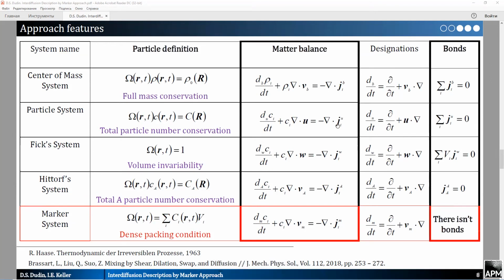The mass balance equations for components written in terms of the total time derivatives have the same structure for all systems, but they differ only in the macroparticle velocities. For example, in the center of mass system, there is the barycentric velocity, and correspondingly in the marker system, there is the marker velocity. In this regard, both the diffusion fluxes and the total time derivatives will differ during the transition from one system to another.